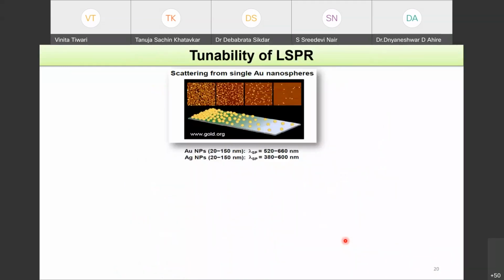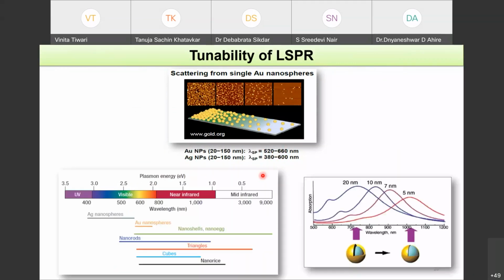And what about the tunability? Yes. The resonance is tunable with the size of the nanoparticles. If you take different sizes, you can see that for gold nanoparticles and silver nanoparticles, you can have resonances ranging up to 600 or 660 nanometer. These are the ranges supported by silver and gold nanospheres.